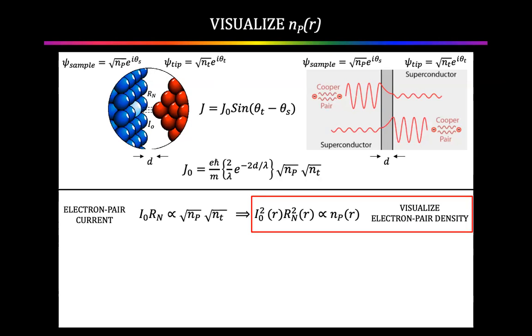There's a Josephson current density, which has to do with the geometry of the junction, the energy barrier, the work function, the cross-sectional area, multiplied by what is usually called the product of the two order parameters. In the Ambegaokar-Baratoff theorem. But actually, that's the square root of the density of the condensed pairs. That's the way I'd like you to think about it. In a BCS, that would be correct. Expectation value squared of c_i dagger c_j is the number density in BCS.